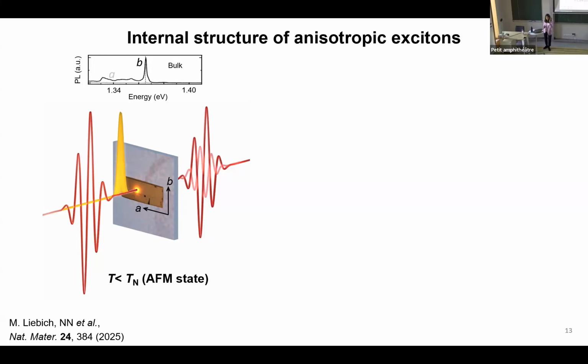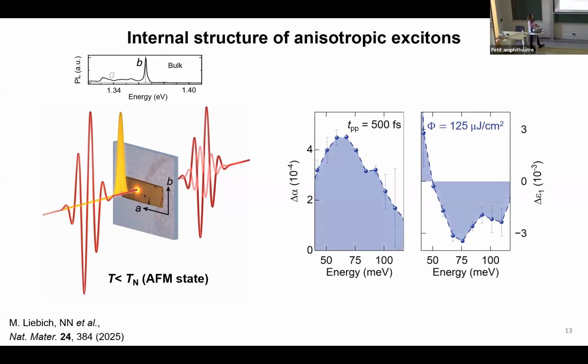So we put the mid-IR probe polarization along the B direction, and we pump our material with near-infrared radiation to generate excitons and to see where these transition energies are located. We see a peak appearing in the pump-induced change of the absorption at around 60 milli-electron volts, and we have a corresponding dispersive behavior at this energy in the real part of the dielectric function. So there must be an excitonic transition that I attributed to the 1s-2p_b orbital transition.